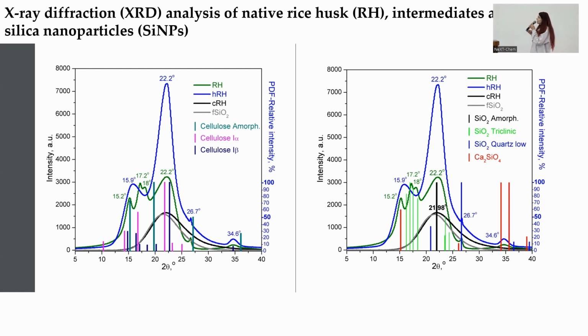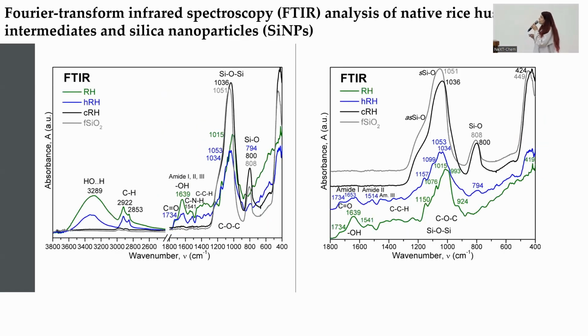With respect to crystallinity, there was an increase after the hydrolysis process from 66% in native rice husk to 87% in hydrolyzed rice husk, and in calcined rice husk, which are our silica nanoparticles, the crystallinity was only 2%. From FTIR analysis, we can see native rice husk colored in green, the amide 1, 2, 3 protein bands, as well as the carbohydrate bands. And after the calcination, we can also see that the silica nanoparticles are characterized by the Si-O-Si and Si-O bond vibrations.